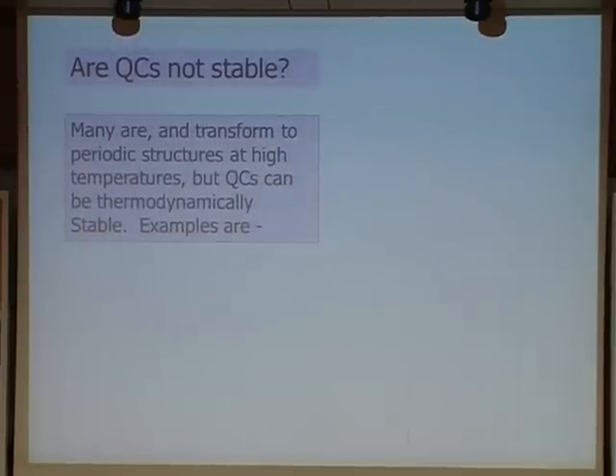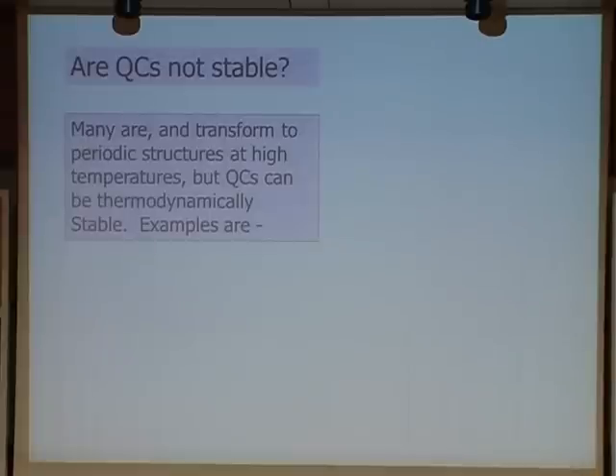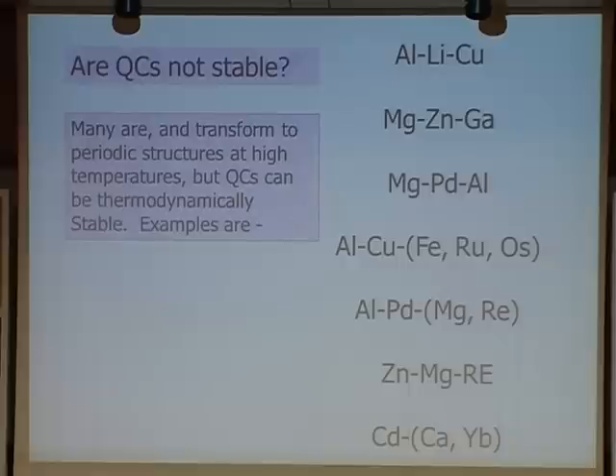Maybe they're not stable. Well, many are indeed not stable, but what does it mean? It means that when you make them, let's say by rapid solidification, which is a commonly available technique, they are stable at room temperature. You have to heat them up to 300, 350, 400 degrees, and then they transform. But at room temperature, stable. And then there are stable quasi-periodic materials that melt congruently without any transformation. So that's not the answer.